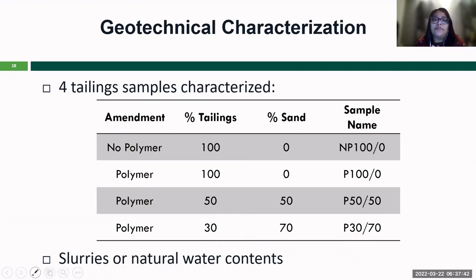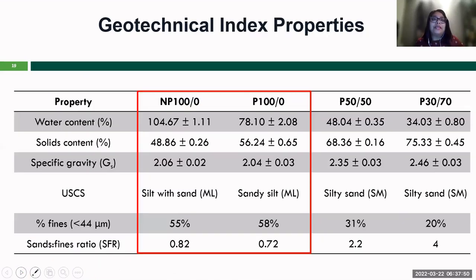Either the tests were performed with slurries, the slurry materials fully saturated, or at the natural water content. So looking at this geotechnical test data, we have a geotechnical test summary presented here. What we have noticed is that the specific gravity we found for the 4 different materials is lower than what we have seen for oil sand tailings in the literature. So this is kind of an interesting fact.